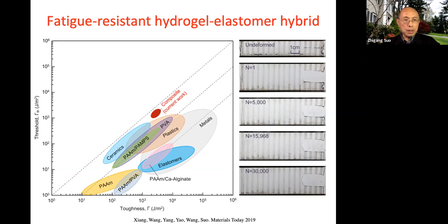so this is the threshold as a vertical axis as a function, and compare with the toughness. We already know for something like a natural rubber elastomer, the toughness itself can be enormous, 1,000 to 100,000 joule per meter squared. This is the elastomer, but the threshold is less than 100. That's the elastomer. But our material can reach a threshold about 1,000, and a very simple principle.